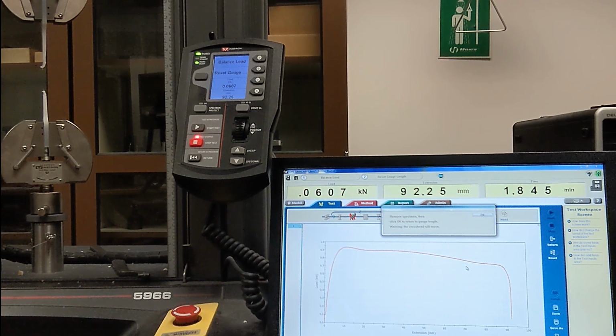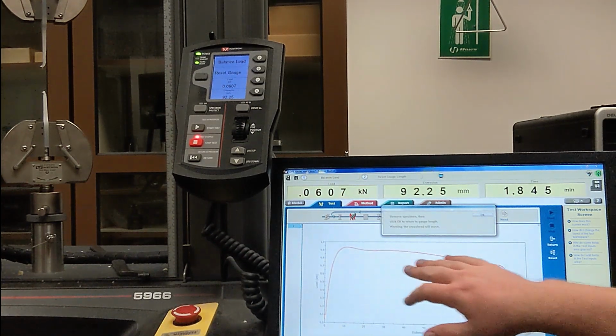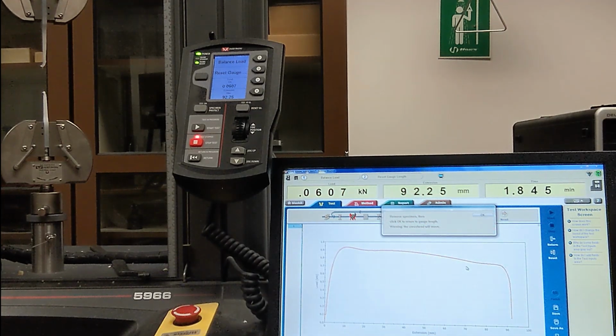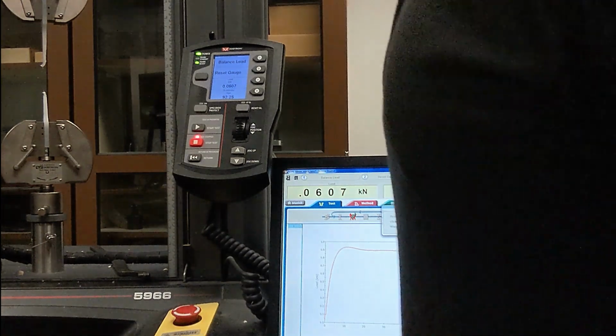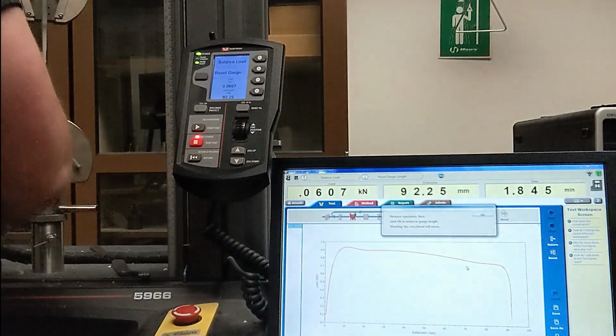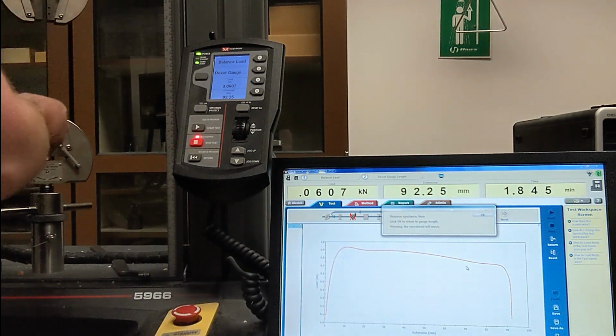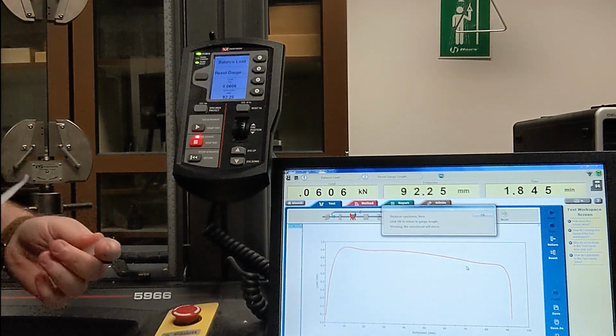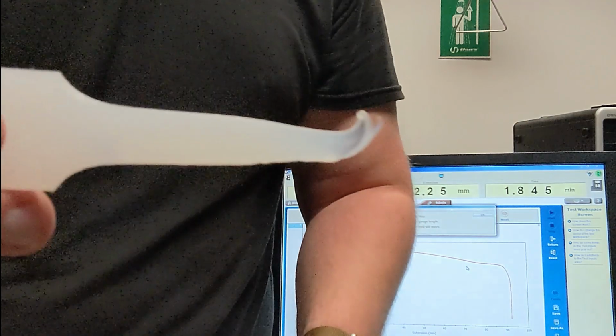Okay, so not quite as much ductility as I expected, but we have an extension of 92 millimeters, so about half of what we saw in our HDPE sample. And here is our sample. And you might be able to notice on the edges here, our sample actually is clear. You can see through it.